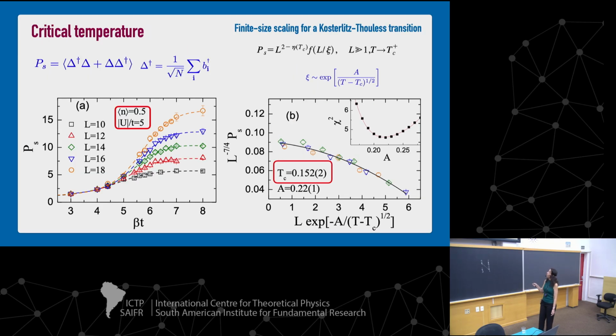So the fact that we are in a Kosterlitz-Thouless phase transition, it has its peculiarity. So we know the finite size scaling when we are in this type of transition. The pairing is supposed to go with L, which is the size of the lattice, to the 2 minus eta. Eta is an exponent that is known to be 1/4 for this kind of correlation, and here a function. And so we try to adjust the TC and here to have them all collapsed, and with that we extract the critical temperature.